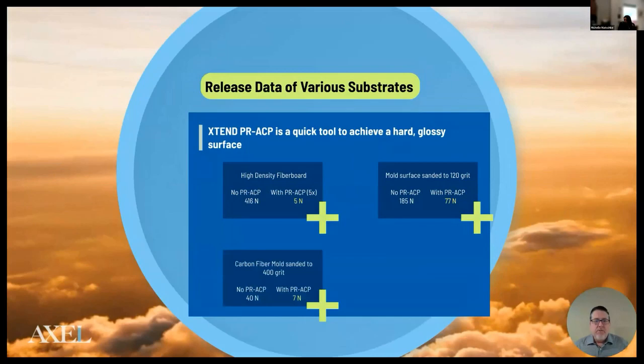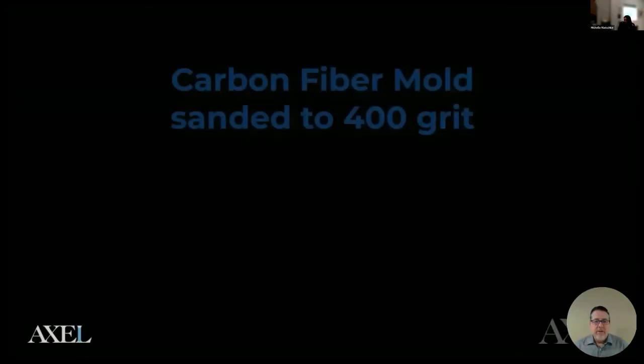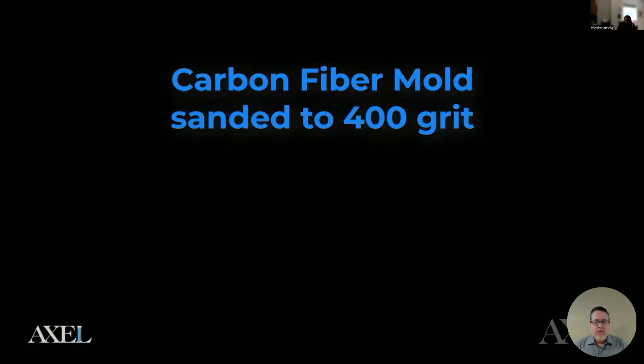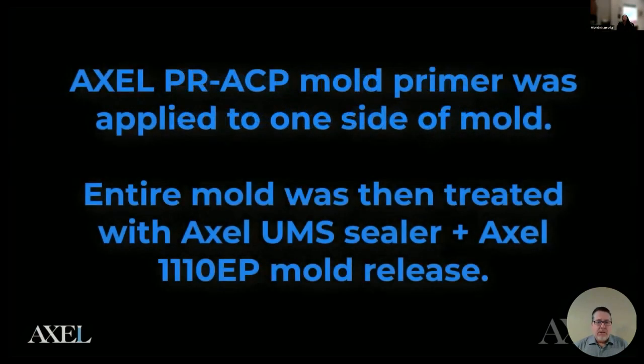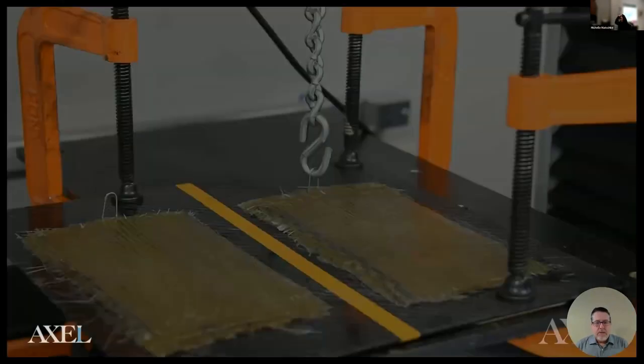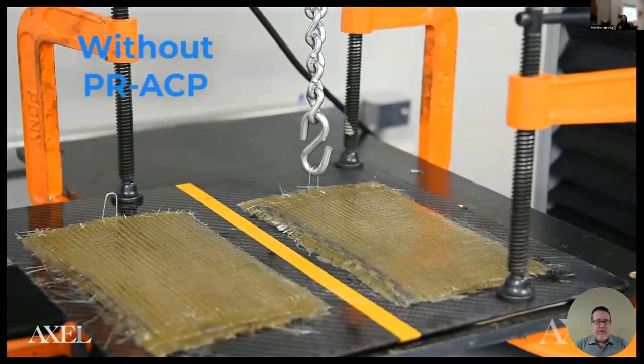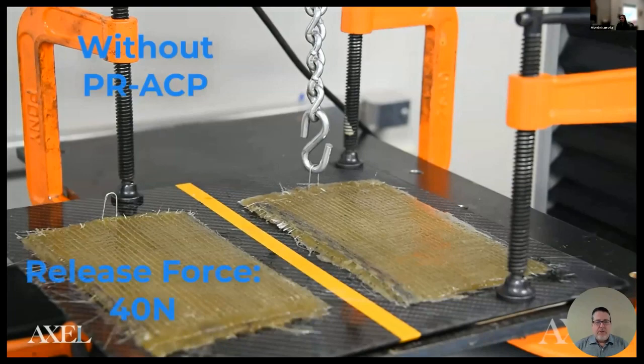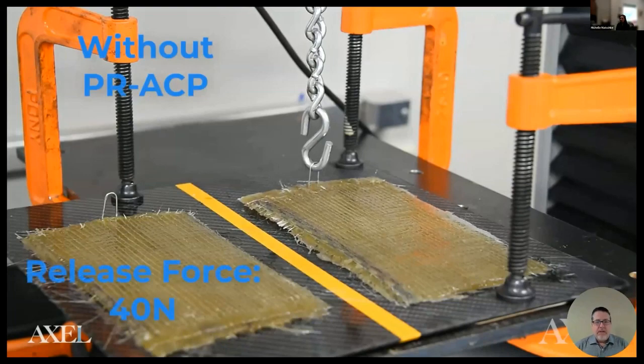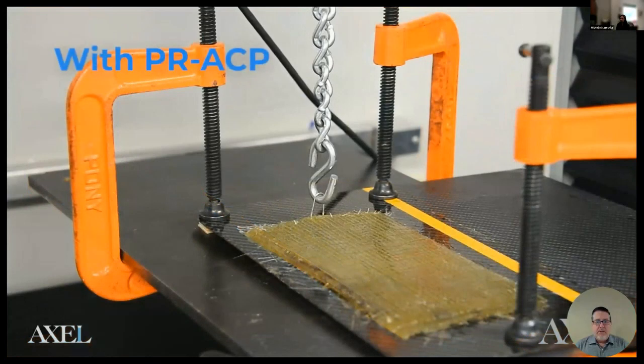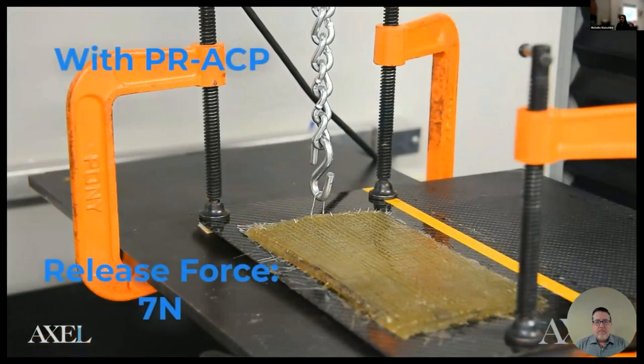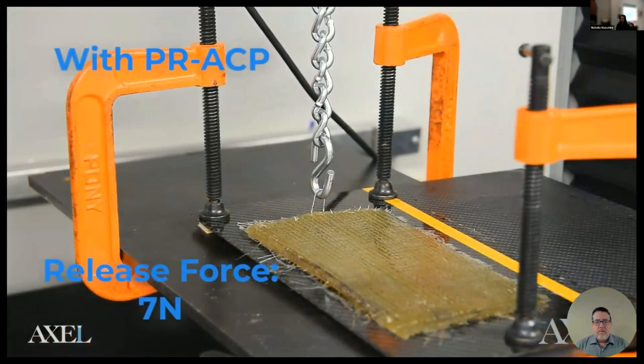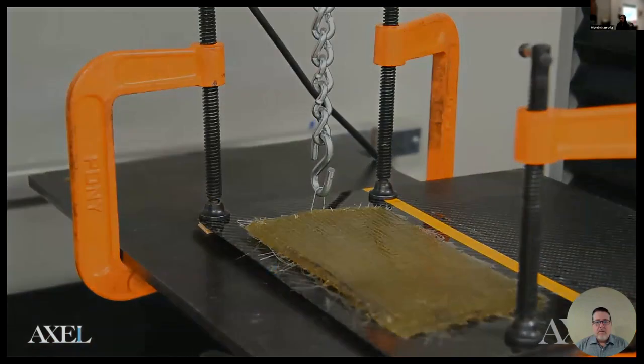Moving on to the third surface, we treated a carbon fiber mold, sanded to 400 grit. And again, with and without the primer, but the sealer and the release applied to both sides. You're going to see a difference as well. It's hard to see the gloss difference, but you can look at the reflection of the clamp on the left side and see a high gloss, and very little reflection on the right side. Quite an easy first release.